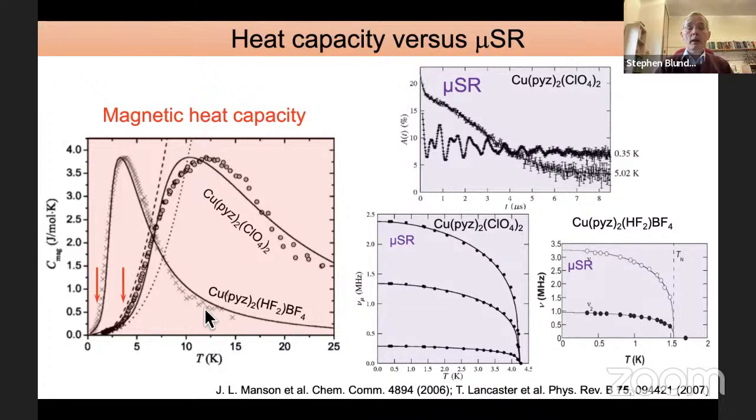But at much lower temperature down here, the system suddenly realizes that it isn't one-dimensional, it's actually three-dimensional. Those smaller couplings become important. And so the system suddenly shows long-range magnetic order. And that means that you get a peak in the heat capacity. But essentially the problem is almost all of your entropy has gone. So there's nothing left for the sample to give. So in fact, there is a tiny kink as shown by those red lines, but really you can't see it. It's almost invisible on these diagrams, the peak there. You know, there is a very small kink there and a very small kink there, but it's really almost impossible